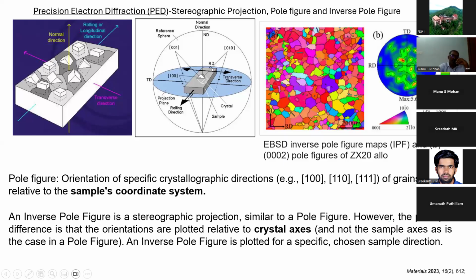So this sphere, and then you plot normals to those planes. So the 001 plane, you project the pole normal from the plane to the reference sphere. You have 001, 010, all planes, you can plot the normals towards the northern hemisphere, and then draw a line from the southern hemisphere to the point of intersection of the normal on the northern hemisphere. When you draw that line connecting the southern tip of the sphere to the point of intersection on the reference sphere, you intersect at a point.